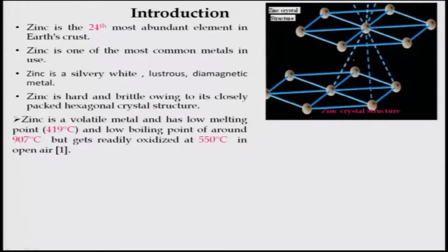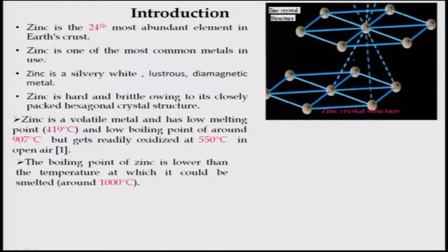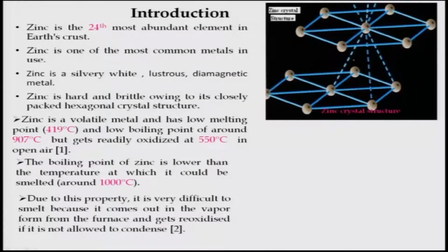Zinc is a volatile metal and has a low melting point of around 419.5 degrees Celsius. Of course, I have written 419 just to make you remember. It has a low boiling point of around 907 degrees Celsius, but gets readily oxidized around 550 degrees Celsius in open air. As a result, it is very difficult to smelt as compared to iron, because the boiling point of zinc is lower than the temperature at which it could be smelted, around 1000 degrees Celsius. As soon as the zinc vapor comes in contact with air, it gets oxidized, and therefore it is very difficult to smelt as compared to any other metal.